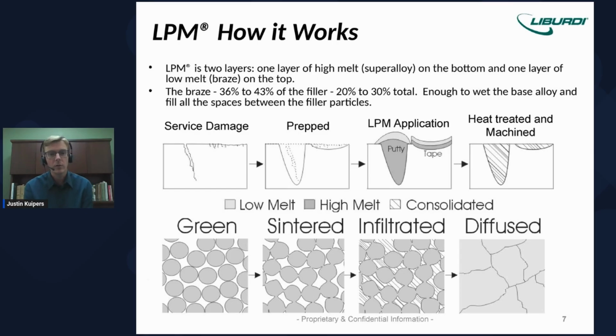Looking at a more microscopic level of what's happening during the heat treatment process, we see at the bottom an example of what's happening with our powder particles. So we start with our high melt filler powder particles packed into our groove. As we increase in temperature during our vacuum furnace heat treatment, we start getting ligaments or sintering happening between our high melt powder particles.